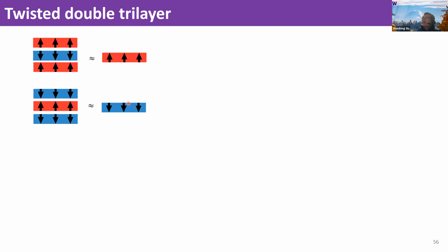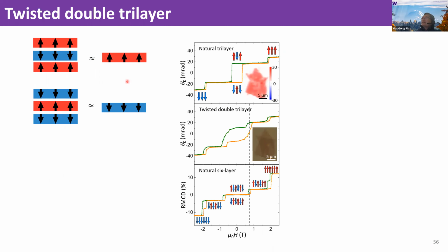Now, if we stack a trilayer on top of a twisted trilayer, we measure these. The top is the Kerr rotation signal of a natural trilayer, and the bottom is the Kerr rotation signal, or MCD, of a natural six layers. And in the middle is the signal from this twisted trilayer.